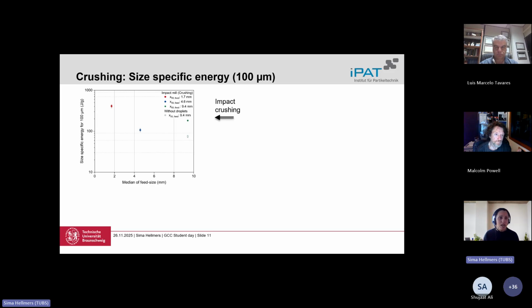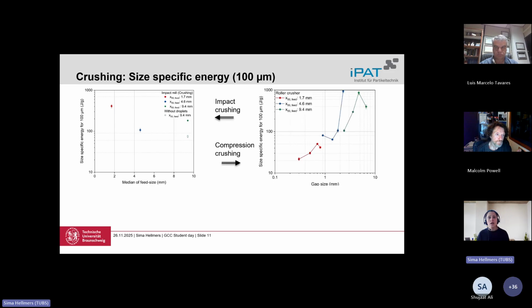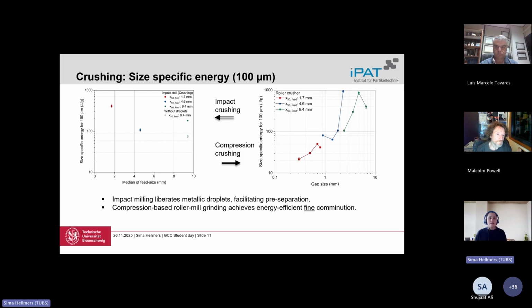So as we can see, impact is not that efficient, but when we look at the compression, we see that for the higher and bigger feed, we have the same behavior. Only when we look at the 1.7 millimeter feed, we can see that we have a better energy efficiency. Another thing that we saw was that with an impact mill for the larger particles, around 1 centimeter, the particle size distribution was a bit strange. There were really big particles, and then there were very fine particles around 1 millimeter.